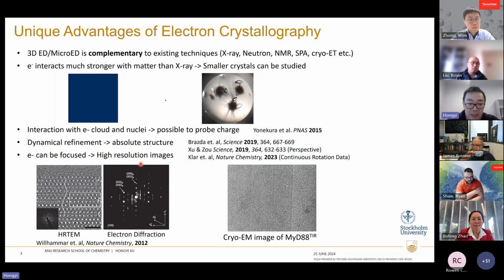And last but not least, electron can be focused, so we can take high resolution images, right? So with diffraction data, we get the average structure of the crystal, but then we can use high resolution images to look at local disorders and local information of the crystal. So this is a very great combination between imaging and electron diffraction. So in all, this is called electron crystallography.